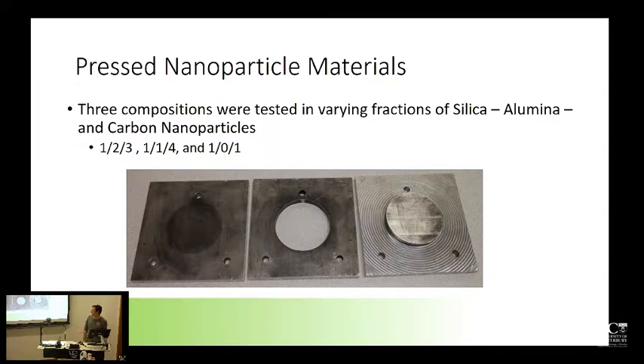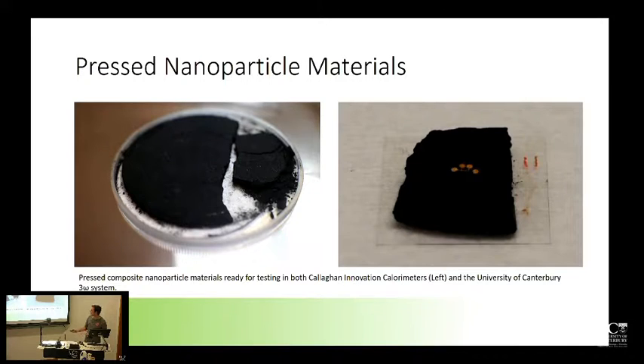That's why we made this big aluminium press, which was CNC machined in the nano lab. We would load a whole bunch of materials and then squeeze it to some incredibly large pressure in the megapascal range, and then we would get out a structure which looks like this. The cracking was included there intentionally in the photo, because the pucks that we got out of it were incredibly brittle and incredibly hard to deal with. What I ended up doing is slicing them into smaller chunks which we could then affix to something and make a little bit more mechanically stable.